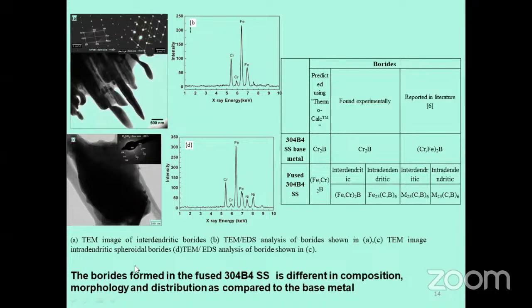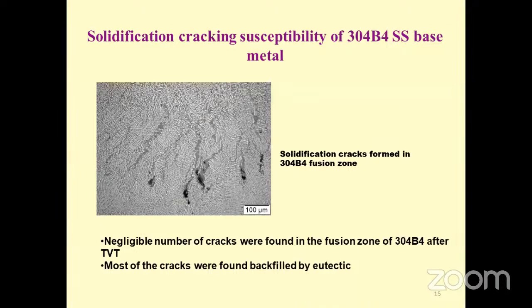So what we can infer from this study is that the borides formed in the fusion zone of borated stainless steel are different in composition and morphology compared to the base metal borides. Now coming to the solidification cracking susceptibility of the base material. When we did the Varestraint experiment on the base metal, once the 304B4 material solidified, we see that the cracks are getting backfilled by the eutectics formed in the fusion zone during solidification. You can see these dark black regions are the cracks, and these were backfilled to some extent by the eutectics formed in the fusion zone by capillary action.